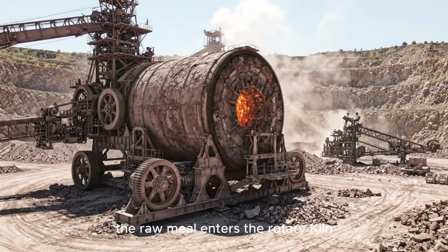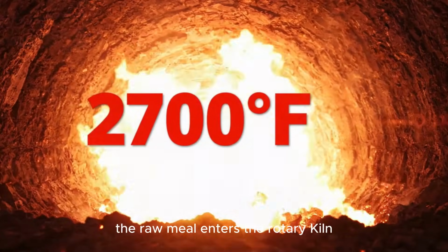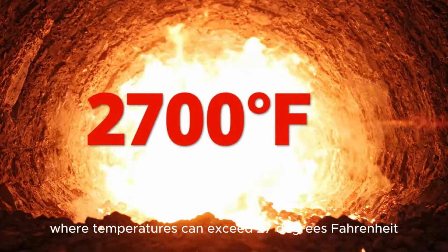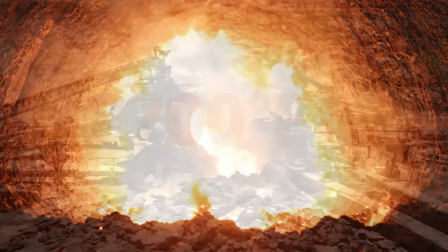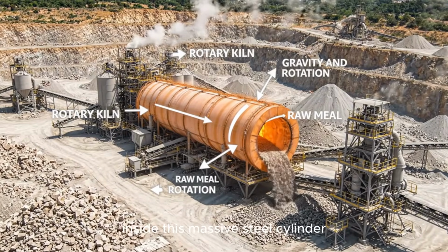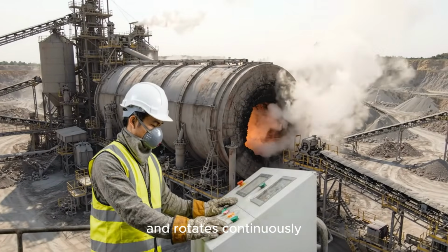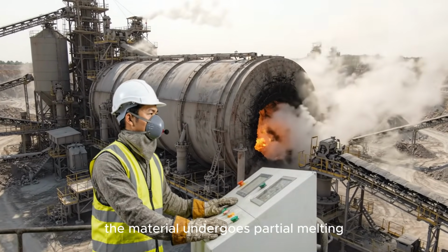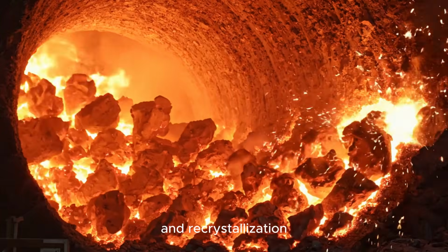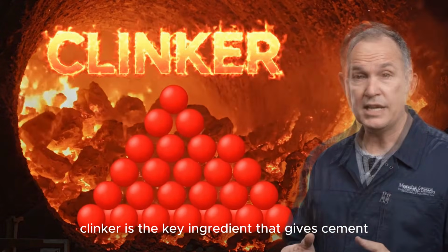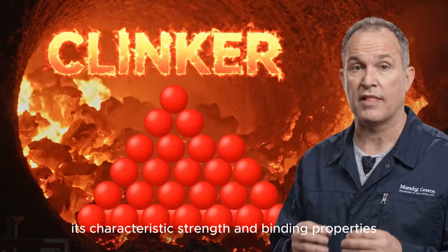Leaving the calciner, the raw meal enters the rotary kiln, where temperatures can exceed 2,700 degrees Fahrenheit. Inside this massive steel cylinder, which is installed at a slight angle and rotates continuously, the material undergoes partial melting and recrystallization, gradually forming small nodules known as clinker. Clinker is the key ingredient that gives cement its characteristic strength and binding properties.